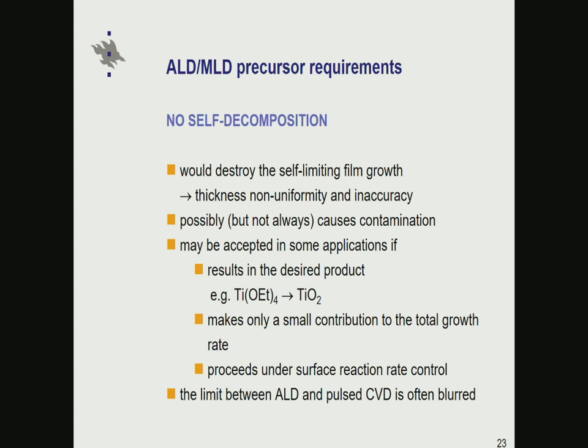On the other hand, we don't need to be strictly ALD in many cases or for many applications. If you think about, for example, corrosion protection coatings, they don't need to be exactly uniform all over the large parts there. We can accept some CVD component on top of ALD component, provided that the decomposition results in the same product as the ALD reaction. For example, titanium alkoxides are used together with water to deposit titanium oxide by ALD, but if going to too high temperatures, they start to decompose on their own, producing the same titanium dioxide. And if this makes only a small contribution to the total growth rate, one has still a reasonably good control over the whole thing.